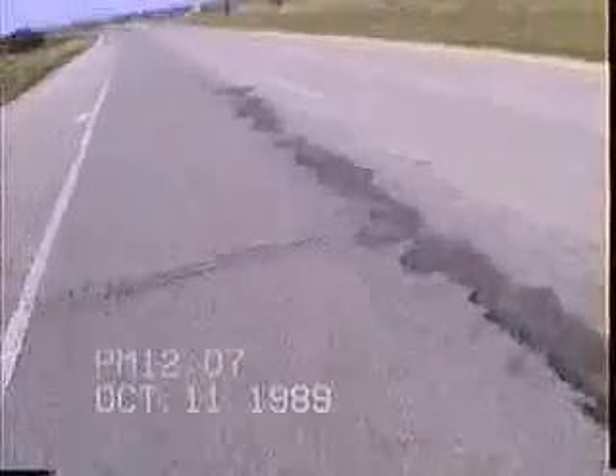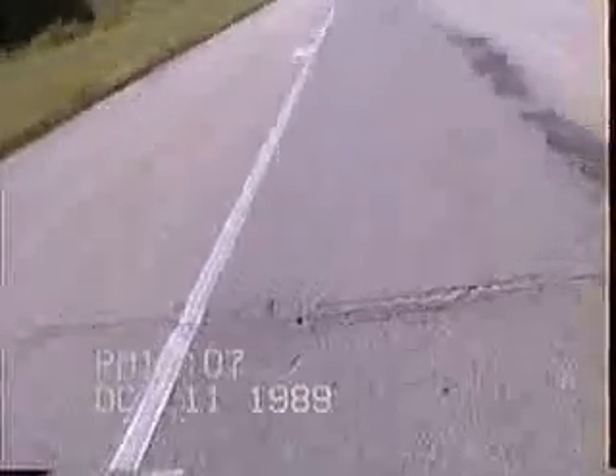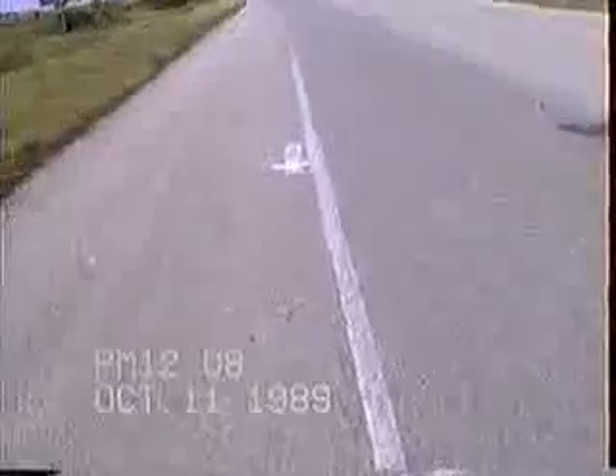It appears to be the same mechanism, though, as we see elsewhere here, where we have these depression cracks. Here is a high severity transverse crack, where it's the moisture infiltrating the pavement causing the rutting, and the rutting actually being due to the erosion of either the sand asphalt or the material in the paved path. And we're back at the beginning of 40C311.